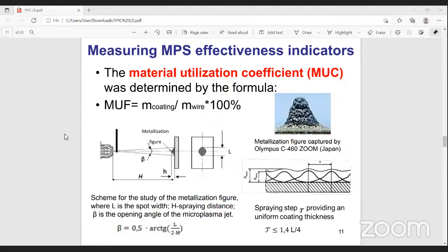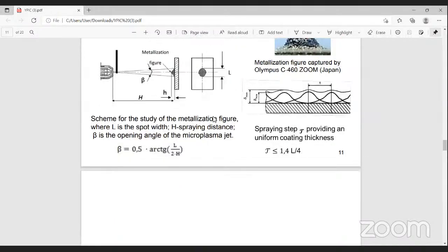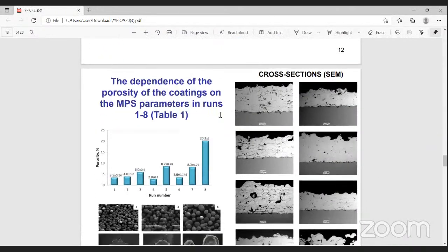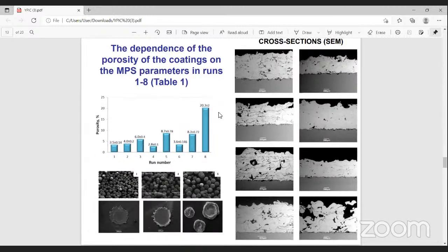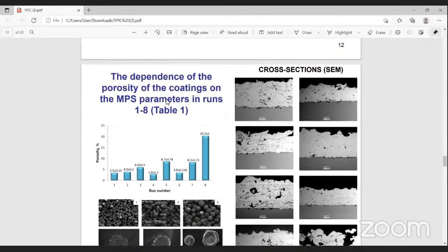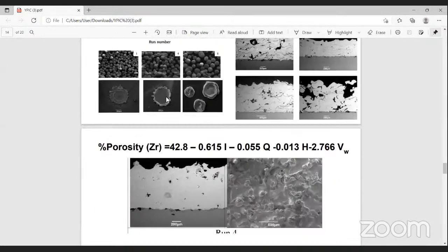Using these coordinates, using MathCAD software, a metallization figure was constructed, and the Gaussian normal distribution function describing it was determined, by which the area of metallization figures was determined. Here you can see the dependence of porosity of the coatings on microplasma spraying parameters in different runs, and the cross-section images.